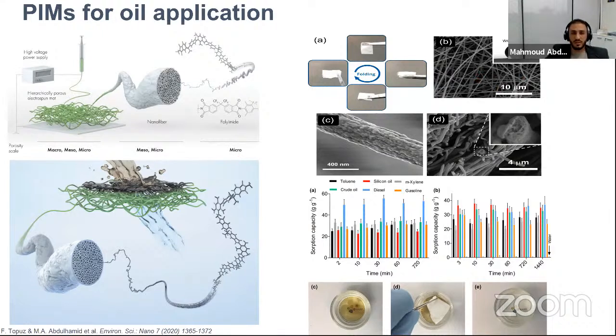We have used this to separate water from oil, toluene, silicone oil, metaxylene, crude oil, diesel, and gasoline, and it performed very well. By looking at these figures, you can see we have oil on top of the water, and once we throw this membrane on top of it, all the oil will be attracted to this membrane, and we have clean water afterwards. So this is one application, which could also be interesting for environmentally friendly applications.